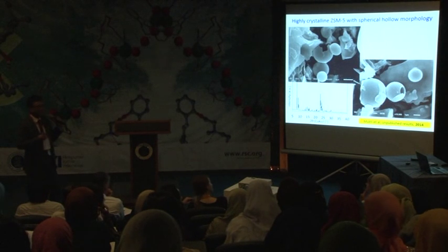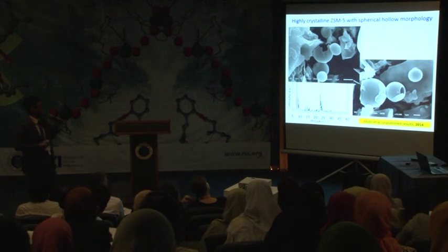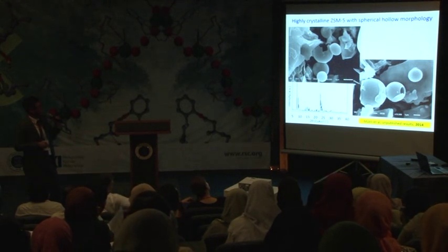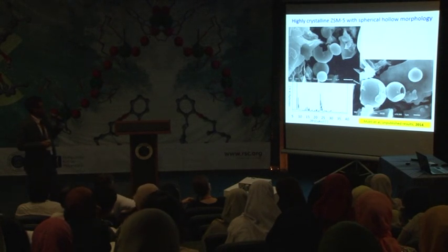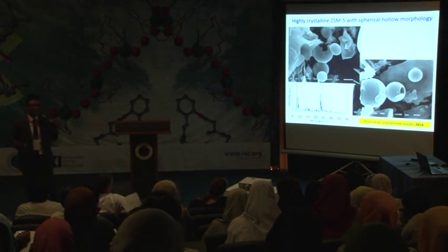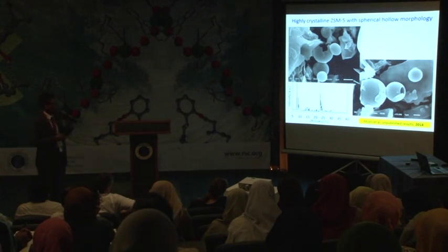Especially this was synthesized in the absence of template, but in the presence of surfactant, of course, because we were talking about surfactants. And we could get the hollow MFI morphology, a hollow spherical morphology, that is very unusual, and probably it would be good for making a complete hierarchical porosity of zeolite, containing macroporosity, mesoporosity, and of course the microporosity in zeolite.